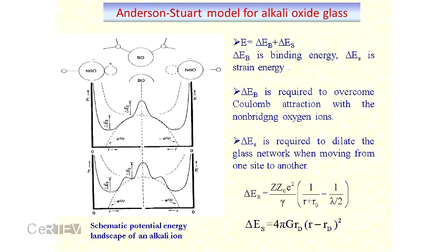Now, we can also describe the motion of ions in a glass structure separately. Practically, you can see there are bridging oxygens, which take part in bonding, and non-bridging oxygens, which are not taking part in bonding and form ionic bonds. When an ion moves from one place to another, we require two energies. One is the binding energy, because you have to separate it from its bond with these non-bridging oxygens. The other is to move through the bridging oxygens. If the opening is shorter than the diameter of the ion, it cannot move, so it has to dilate this structure so that it can move. So it requires some strain energy.